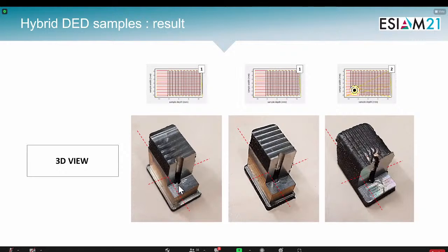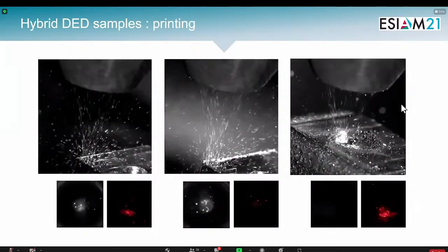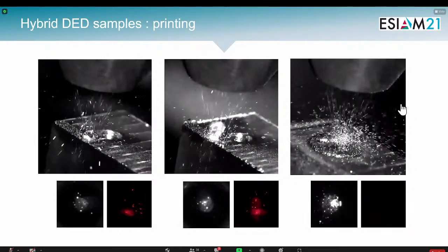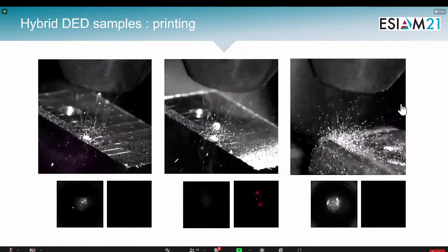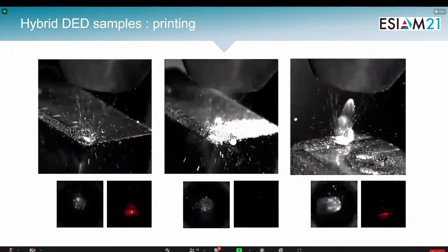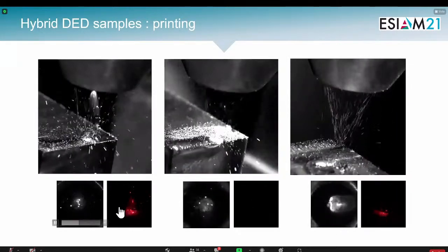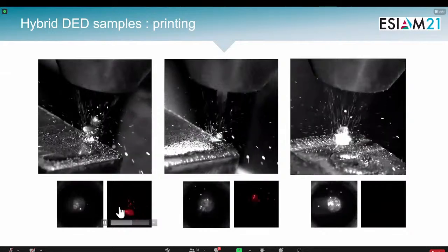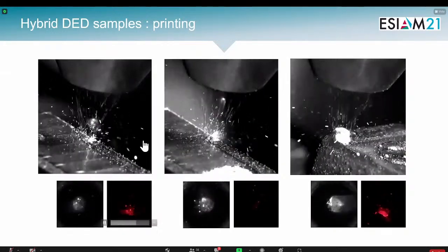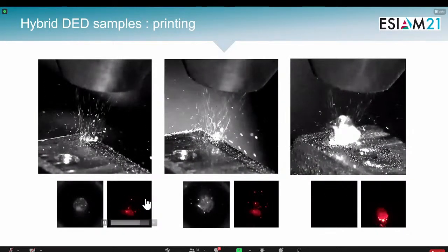And you see the integration of the capillary that is around 3 millimeters through the different sequences that were printed, both here with the first proposed strategy and this one with the second strategy. And you can see here some in situ monitoring during the print process itself. So some images are taken coaxially through the nozzle here to see the quality of the melt pool. And these are taken from the nozzle head.